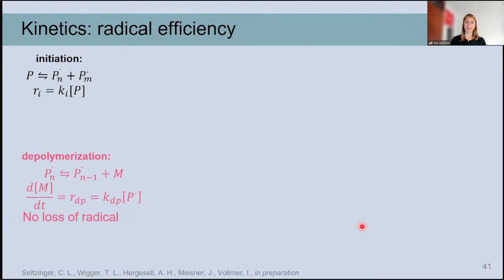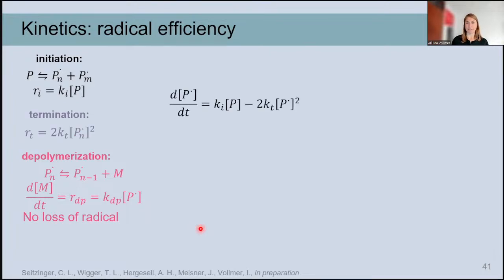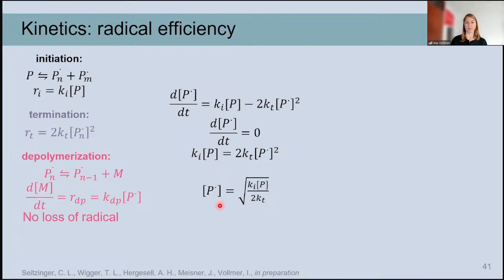We look at the competition between these two reactions by looking at reaction rate constants, these Ks from literature. What we assume here is that we are in steady state, so that the radical concentration in the system is always the same. So the change in radical concentration will be the initiation minus the termination. If we set this to 0, then we can derive the monomer formation. So the radical concentration as a function of the initiation rate, this K_IP, and the termination rate constant that we got from literature. Then the monomer formation rate is this, which is also dependent on the reaction rate constant for the depolymerization. So just from getting literature reaction rate constants, we can now see whether this matches with our values that we obtained in the ball mill.